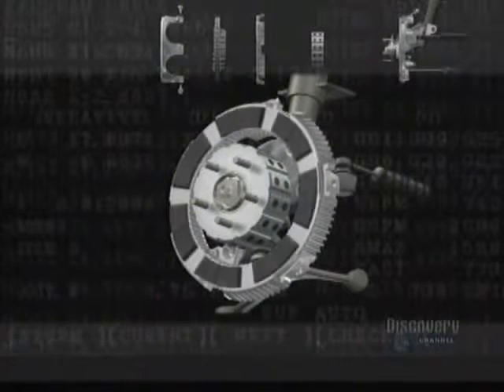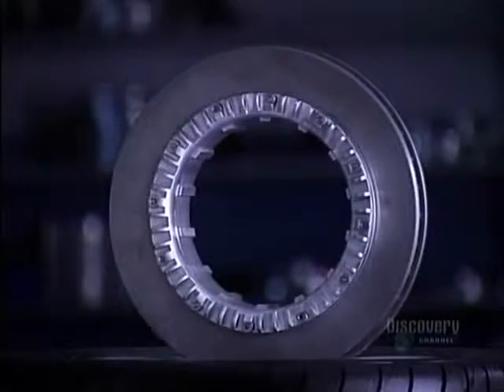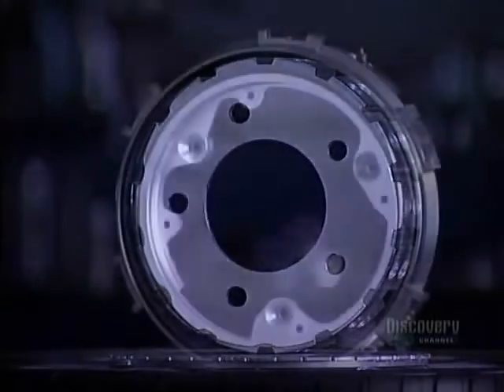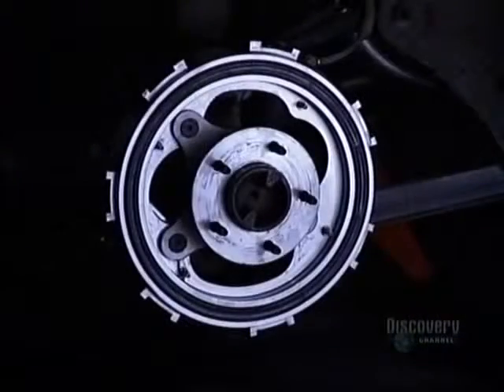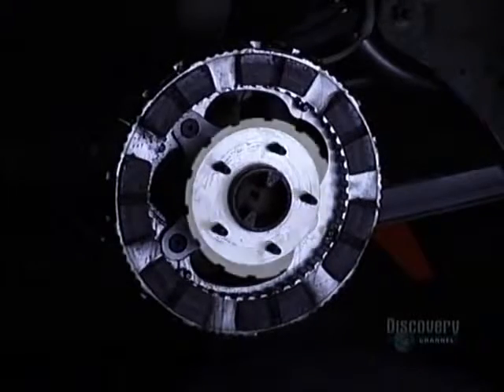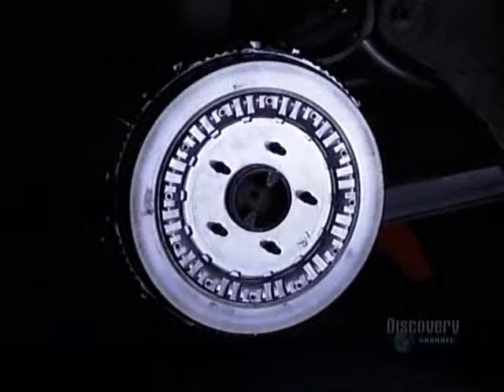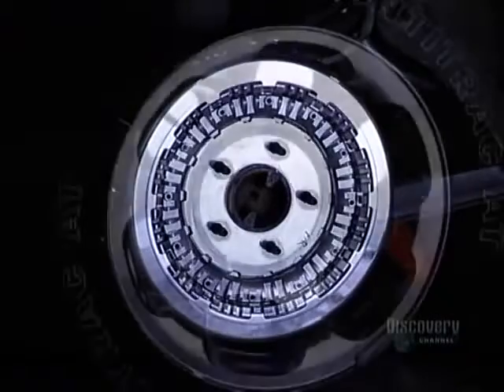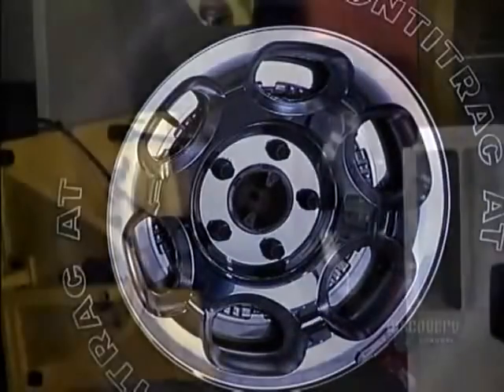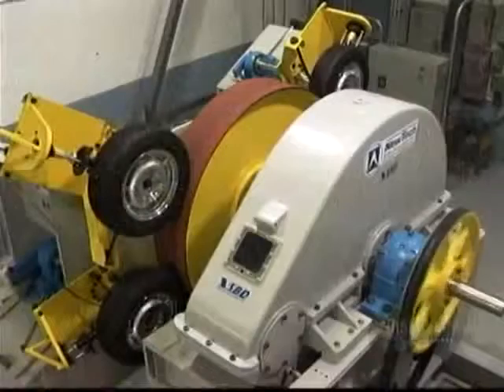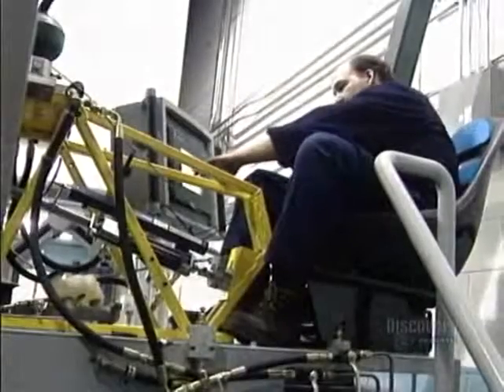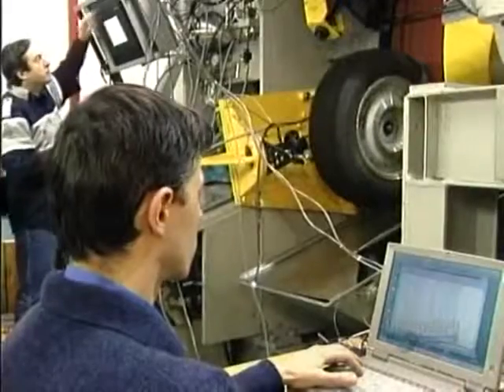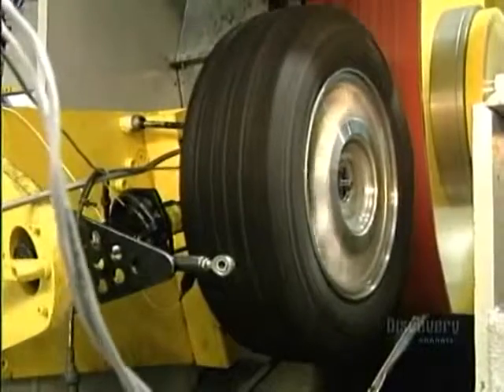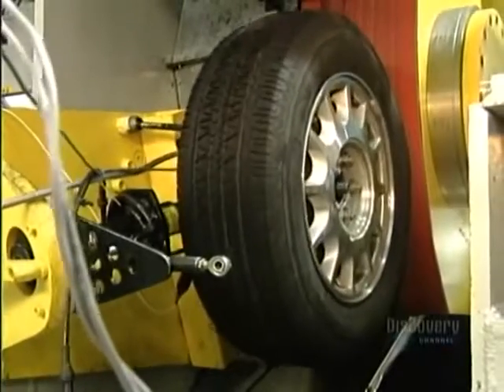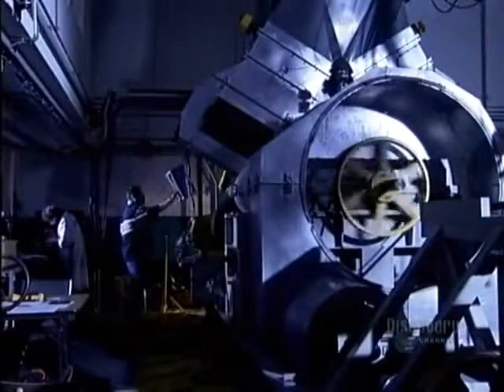Brakes in full contact have a friction surface 6 times superior to traditional brakes. The use of aluminum and composite materials allow for a weight saving of 2.5 kilos per wheel. This affects road holding and reduces fuel consumption by 0.1 liter per 100 kilometers. They proceed to power and endurance tests on this dynamometer, in which a brake and wheel assembly act against a large rotating drum. These lab tests are critical since they can detect any defect in a braking system before it's installed on an actual vehicle.